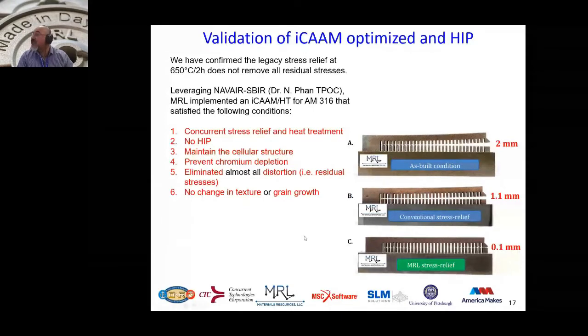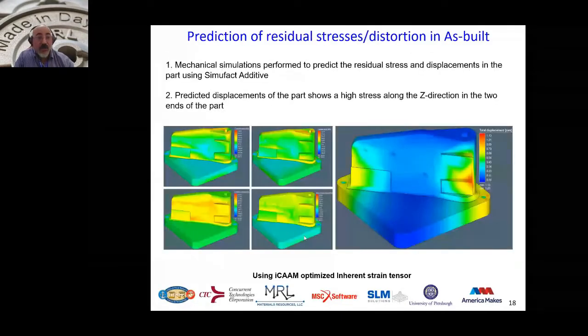This is the implementation on the actual part of this information. When we are developing it, we are able to handle any arbitrary shape, and we are using an optimized inherent strain tensor that takes into account the scanning strategy and the thermal profile, and allows us with that to see the location of the highest residual stresses and the highest distortion. That's even before implementing our optimized heat treatment.